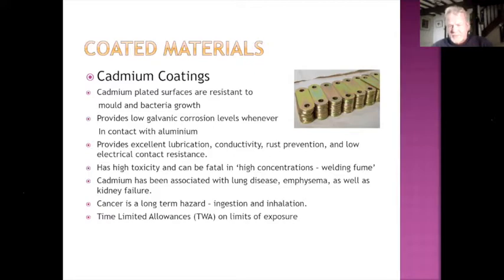All of the cadmium coated surfaces are resistant to mold and bacteria, so you can see that it lends itself to mass production. Many of you will have come across nuts and bolts and little brackets and stuff like that which have all got this almost rainbow effect. It's a sort of goldy color, and that is a cadmium coat. It provides resistance to corrosion. It also forms a bit of a barrier when it's in contact with aluminium, so you don't get the decay that you might get with aluminium. It's a great lubricant, and it's got low electrical contact resistance. It has a high toxicity and can be fatal in high concentrations when welding.